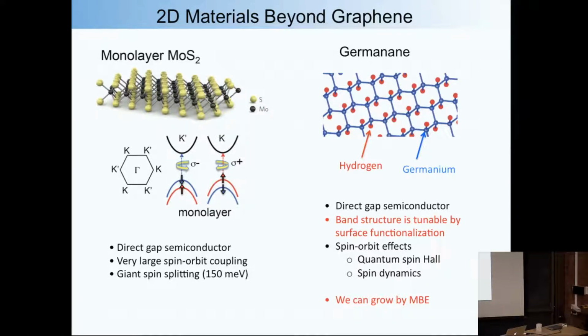Yeah. And so theoretically, the fact that you have some huge internal field, that's going to suppress lots of spin relaxation processes, like the Dyakonov-Perel type. This internal field is so huge that those are all wiped out. And then things like spin flip scattering, even if you dope it exactly with the Fermi level up here, you're going to inhibit it because it can't flip into there, and it actually has to cross the Brillouin zone to get a spin flip. So there's only certain types, like atomic magnetic scatterers, that can cause that, but a lot of spin flip scatterers won't satisfy those conditions. So at least theoretically, this should give longer spin lifetimes.